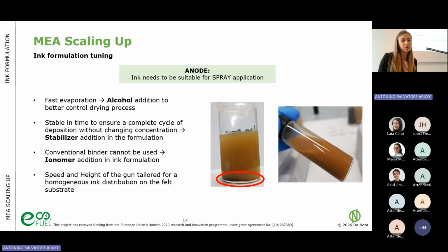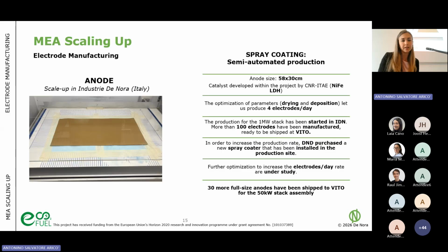And also we saw that we couldn't use the conventional binder that we normally use in our ink at Nora. But what we did was to add the ionomer, as was already said before, in the ink formulation. So those help us both for the stability, but also with the ionic conductivity of the whole structure. And again, another parameter that we need to optimize is the speed and the height of the spray coater on the substrate.